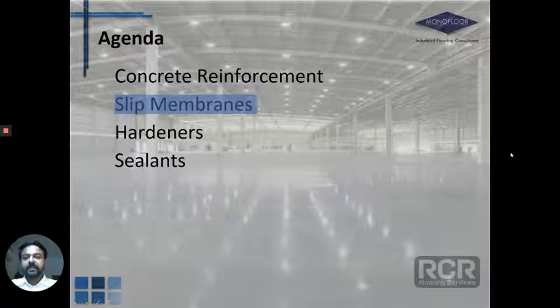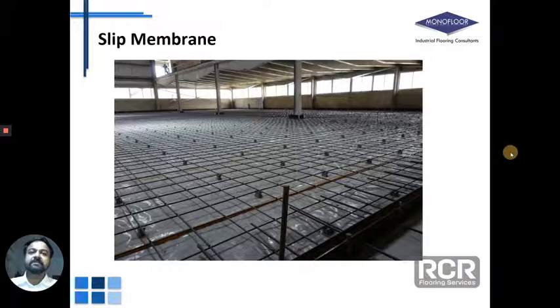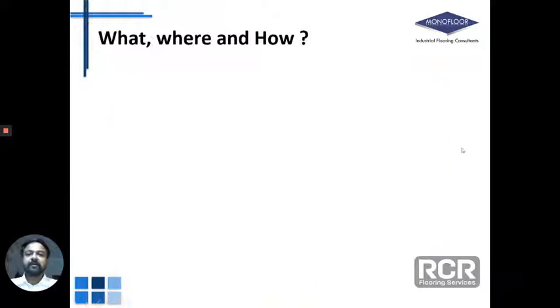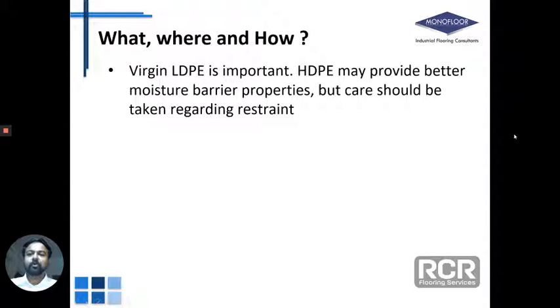Let's talk about the second material that we were scheduled to talk about, that's slip membrane. Many times there are a lot of misconceptions when it comes to slip membranes. Slip membranes are simply the plastic sheet layer that go on top of the subbase, just below the final concrete layer, that is the final floor concrete. Virgin LDPE is the most important aspect when it comes to choosing these slip membranes.